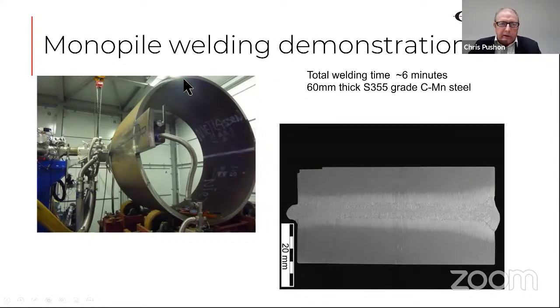And this is a 2.3 meter diameter can. And the aim was to demonstrate how quickly we could make a weld seam in the longitudinal component. And the conclusion was that we could. This is 1.7 meters long, so it's only a short component. And we found that it would take, from beam on to beam off, actually from system on to system off, 6 minutes.